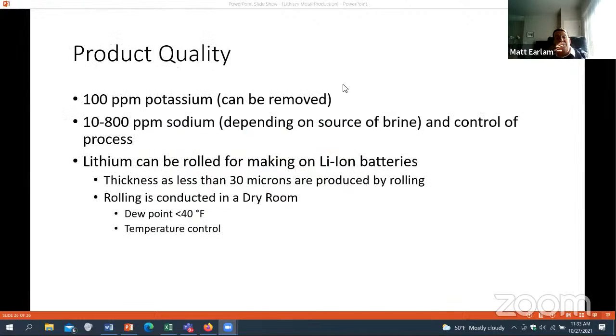So what do you do with this stuff? Well, to make lithium ion batteries, you actually have to make a lithium foil and laminate it to a copper backer. In some cases, they just use graphite, but in the applications that I'm involved in, we're using a copper backer. Lithium is very soft and very difficult to handle, so you have to roll it. And they typically have to roll this material in a dry room because lithium is so reactive with air. They've been able to get down to less than 30 microns in some cases, rolling to make laminations for batteries.